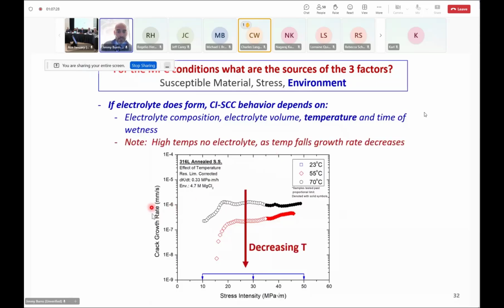Okay, and so this is just an example, again, of crack growth rate. Earlier I showed it for two different materials. Now this is just an example of crack growth rate first versus that mechanical driving force. And this shows there's a very important dependence on temperature, right? And so it can crack faster at higher temperatures, and then as you decrease temperature, you can go down to where actually you don't see any susceptibility, okay? And so what's of interest is you have kind of a sweet spot of temperature, right?